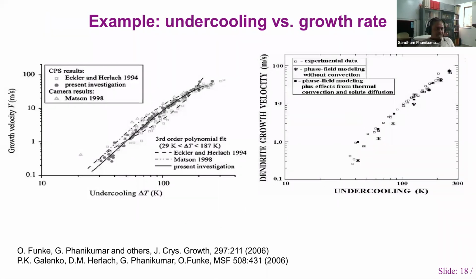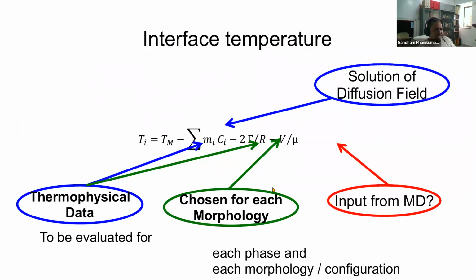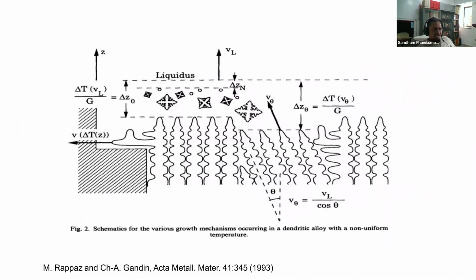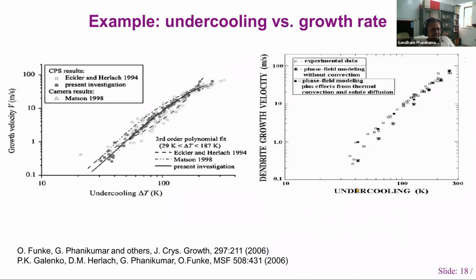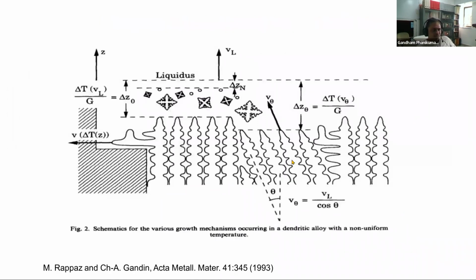Okay, and one piece of information that is also going to come in conjunction with what we have discussed is that the velocity and the interface temperature is related to the undercooling, because as you can see here, undercooling is nothing but the Tm minus Ti. Okay, so the difference between these two is undercooling. So that can be used as one of the parameters on the x-axis, and velocity can be the y-axis, and they can be correlated experimentally. Once you know them, you can make simulations of how the microstructure will form.